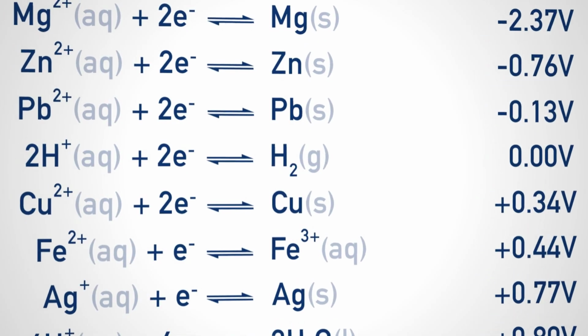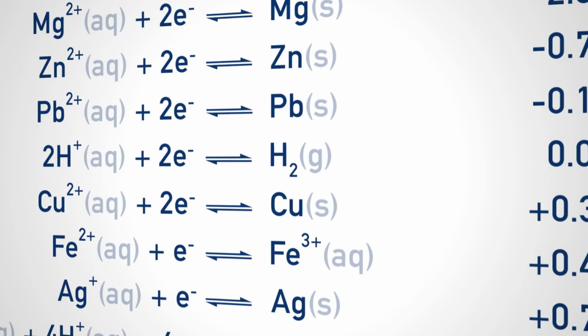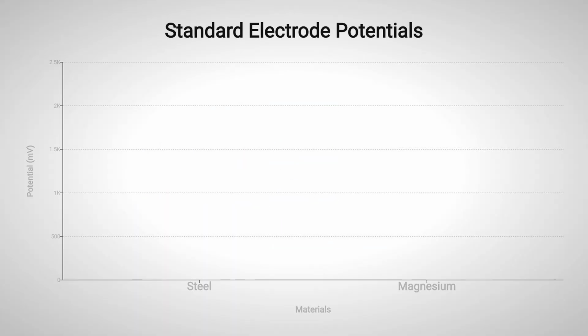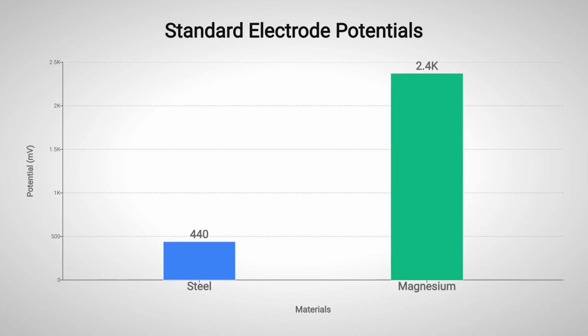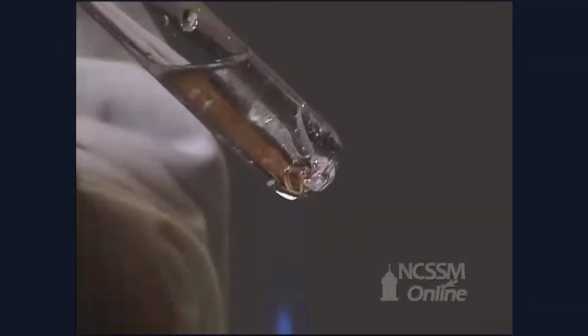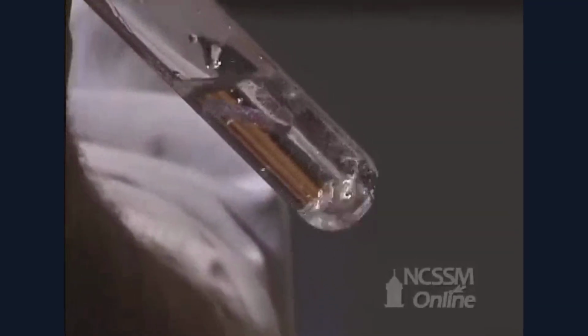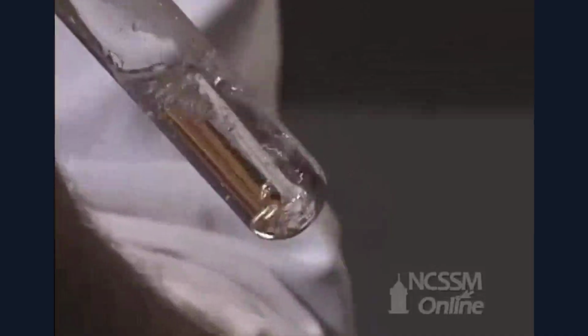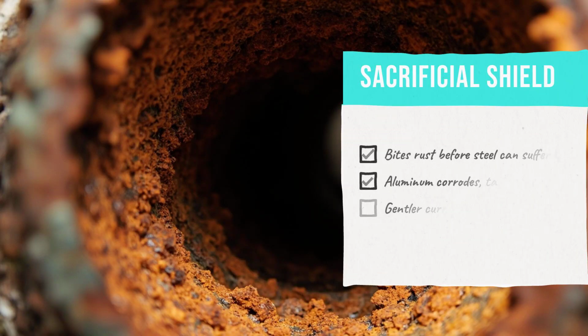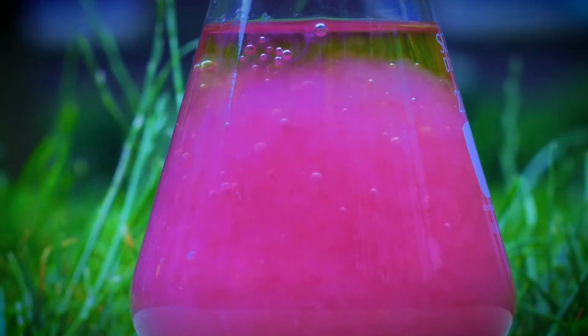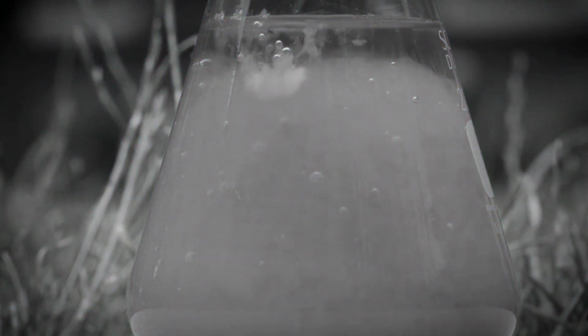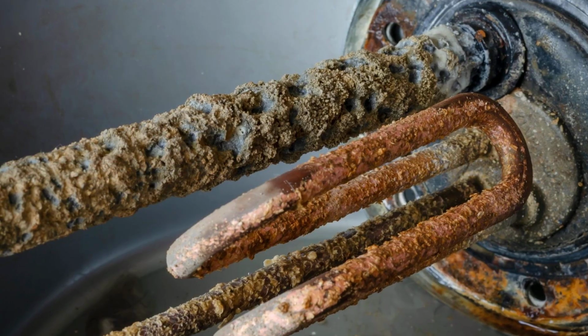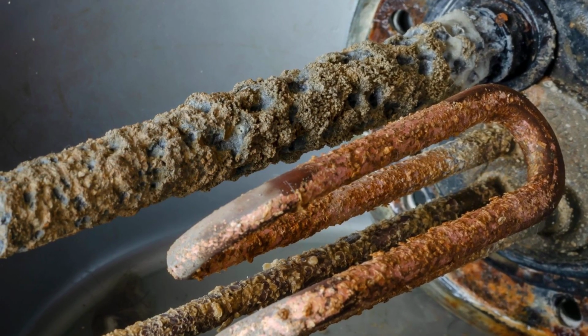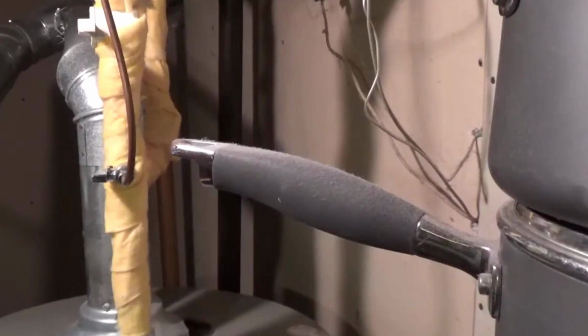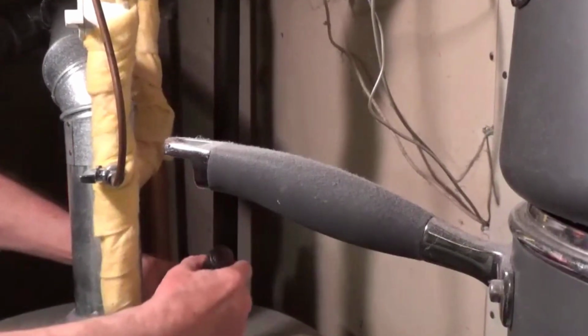The rod's effectiveness depends on standard potentials. Magnesium sits at minus 2.37 volts, far more negative than steel's minus 0.44 volts. That means magnesium always sacrifices itself first. Aluminum is less aggressive but lasts longer in hard water, where calcium carbonate slows magnesium's reaction. The anode rod is the bodyguard, taking every hit until it is gone. As long as enough rod remains, the tank steel stays shielded.